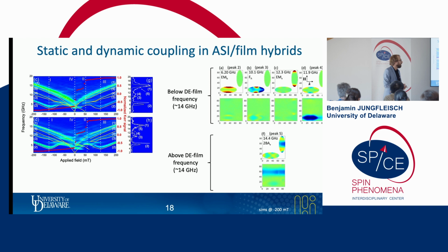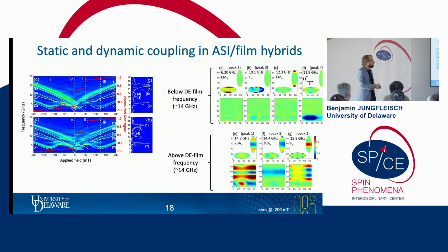So now what's happening when we go closer to the Damon-Eshbach frequency? So when the artificial spin-ice modes are closer to the film frequency. We can clearly see, for example, that peak number 5 is a higher order mode in these vertical elements, and they clearly imprint the same kind of pattern in the film underlayer. There's this same kind of spatial profile. This is peak number 1 at 14.8 gigahertz. We see another higher order mode. The same is true in the underlayer. We see this dynamic vertical coupling between the artificial spin ice and the thin film underlayer.